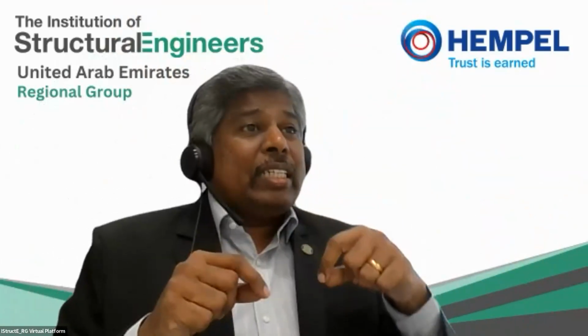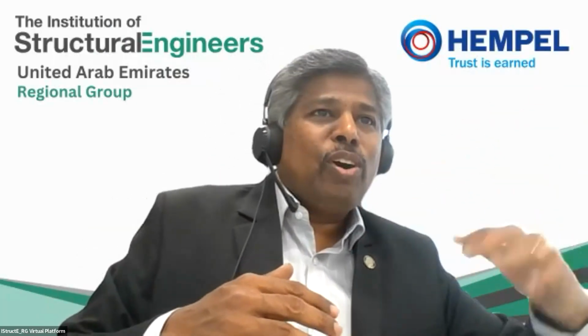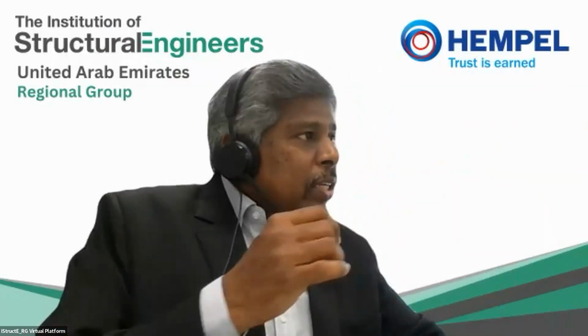So easily moisture and salts can enter, and it can start to creep underneath the coating and delaminate it. In that condition, the zinc rich primer that is applied can make sure that the creep is minimized. Creep underneath the coating is a major problem. That is why, after rust, the coating just peels off or falls down. If you see old structures, the coating peels off because you have creep underneath. So that is primarily the role which the zinc coating does.